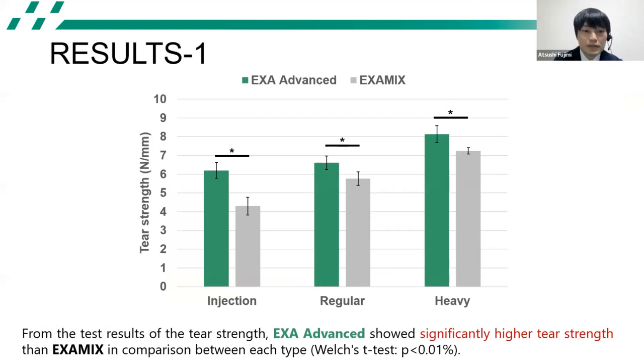Results. From the test results of the tear strength, EXA Advanced showed significantly higher tear strength than Examix. In comparison between each type, I used Welch's t-test.